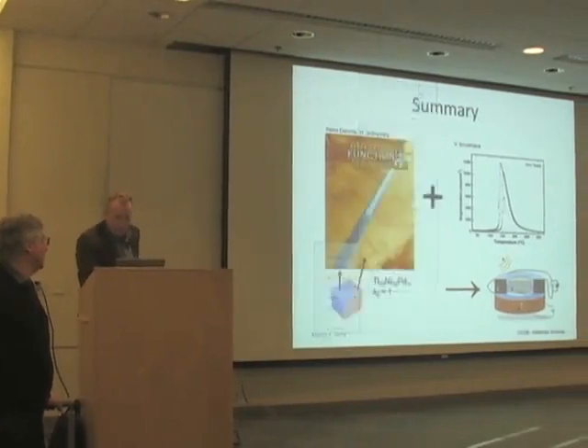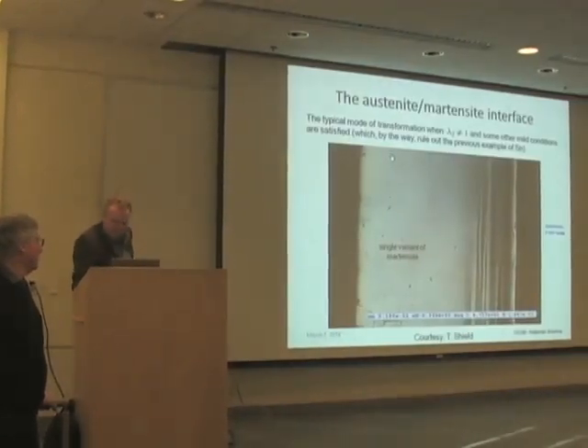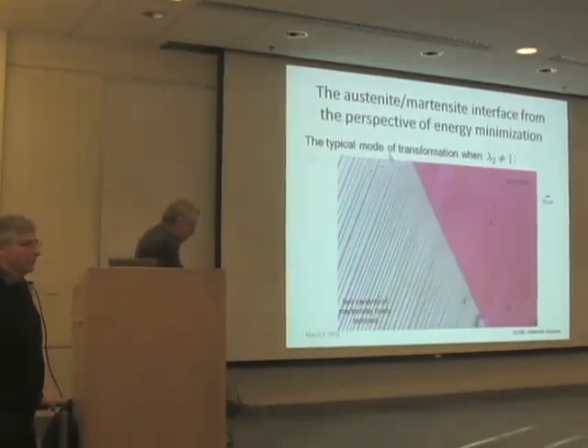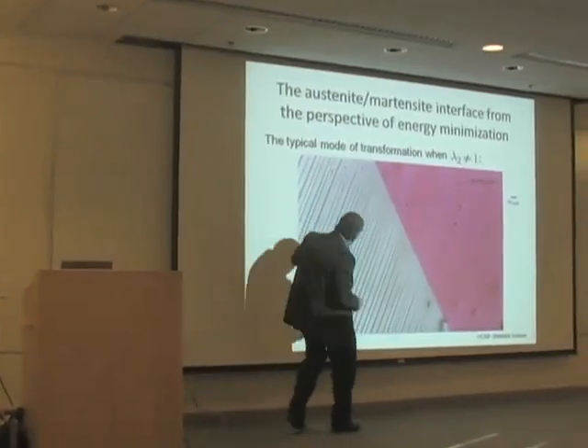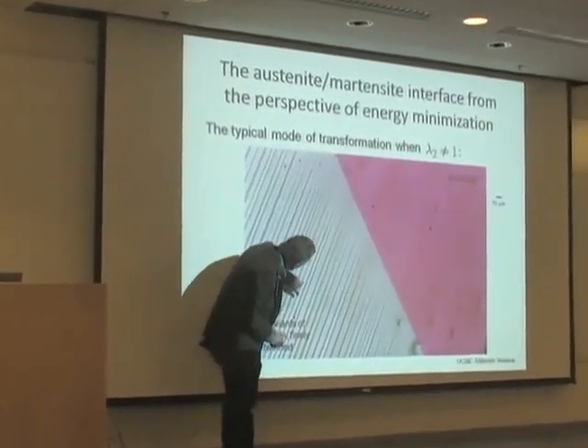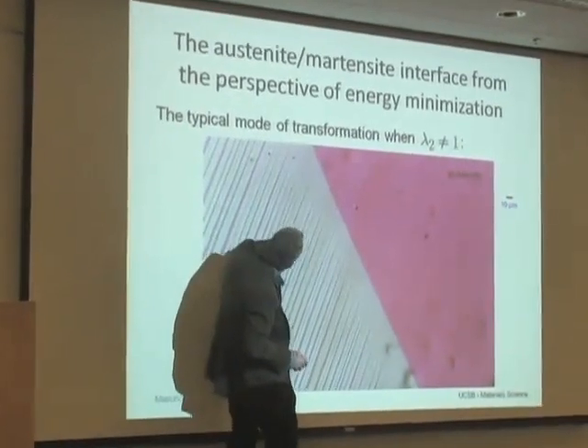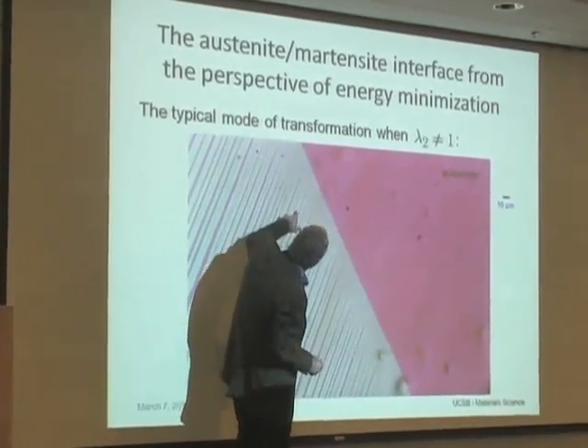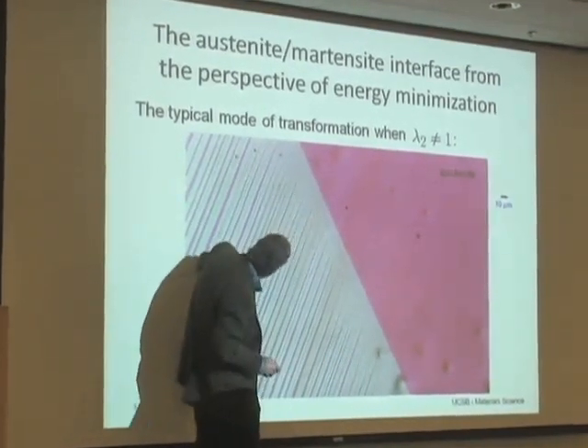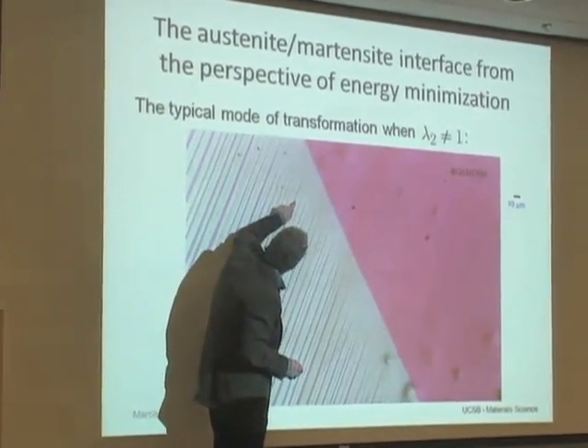Okay, so there's the branching. If you look very carefully, a new band begins there. That becomes, and it splits. Actually, this one is better to look at. So there's 1, 2, 3, 4 bands there, and there's only 2 back here. Okay, so that's the branching phenomenon. But this is a case with lambda 2 not 1. This is a generic case.